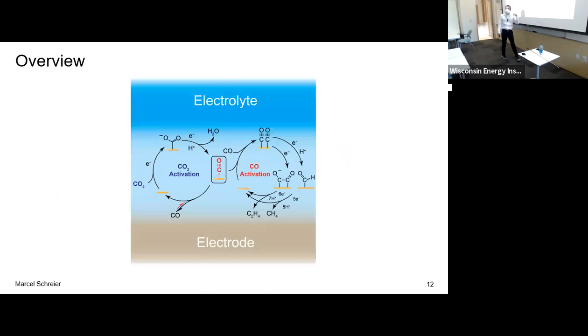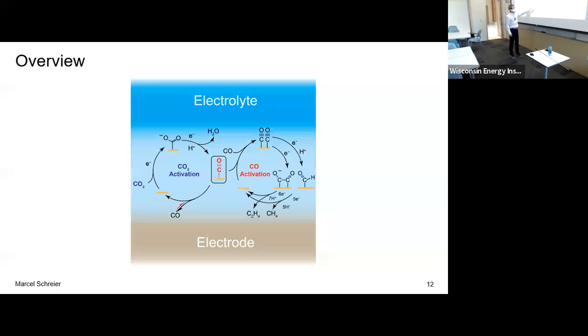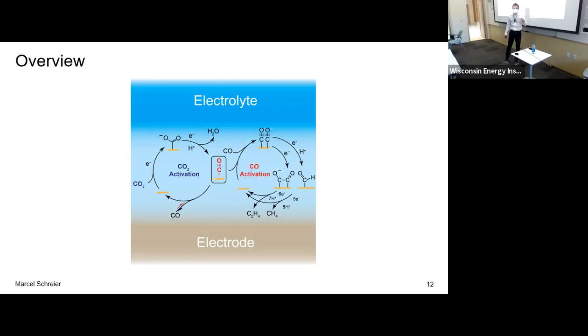Electrochemical reactivity always occurs at an electrified interface, also called an electrochemical interface. This interface is characterized by the contact zone between a solid electrode and an electrolyte material. The electrode conducts electrons, whereas the electrolyte conducts ions. It is at the zone in between these two, when conductivity transfers from electronic conductivity to ionic conductivity, that electrocatalytic reactivity takes place. And if we want to control this reactivity, we need to influence both the electrolyte side as well as the electrode side of this reaction.